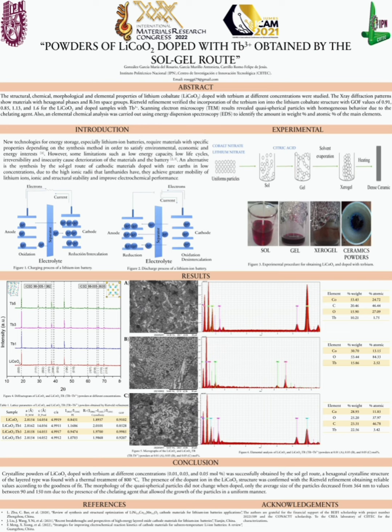The morphology of the quasi-spherical particles did not change when doped. Only the average size of the particles decreased, from 364 nanometers to values between 90 and 150 nanometers, due to the presence of the gelling agent that allowed the growth of the particles in a uniform manner.